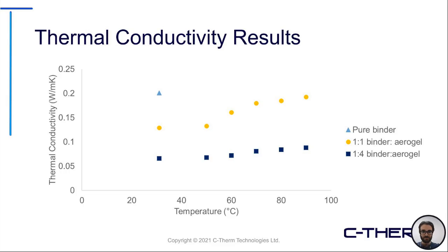Ultimately, what they were able to show is that compared to just the pure binder material without the incorporation of any aerogel, it had the highest thermal conductivity at room temperature. And through the addition of a 1-to-1 and then a 1-to-4 ratio of binder to aerogel, they were able to show an overall net decrease in the effective measurement for the thermal conductivity.